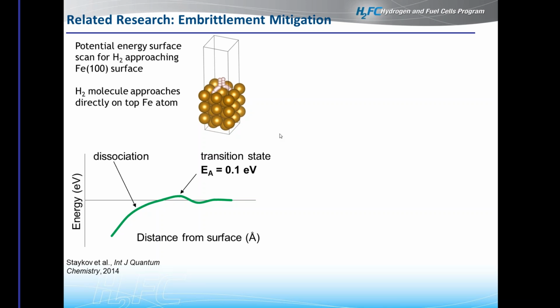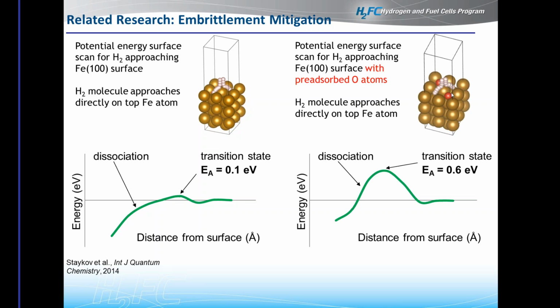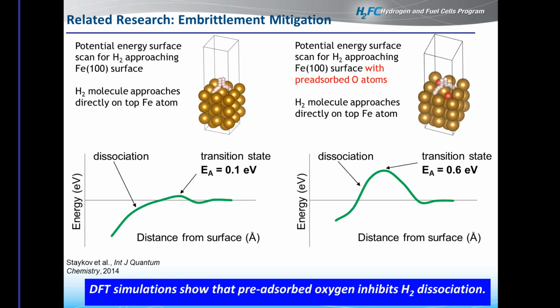If we now look at that same surface, but with the assumption that there was already some pre-adsorbed oxygen on the surface, you can see that in order for this hydrogen to dissociate onto the surface, the activation energy is actually increased. So using density functional theory, it already tells us right off the bat that just having the presence of oxygen already pre-adsorbed on the surface makes it more difficult for that hydrogen to get in. So we wanted to take this type of analysis and do some experimental work to try and verify it. And this was then built into a model with several of our collaborators.